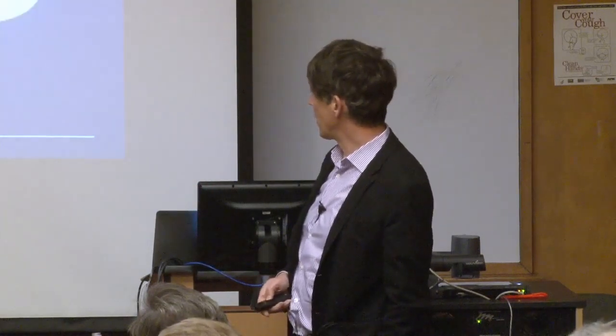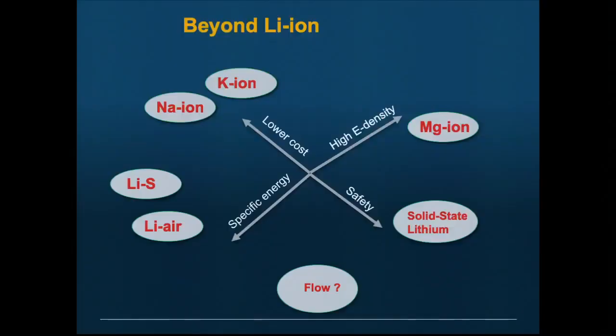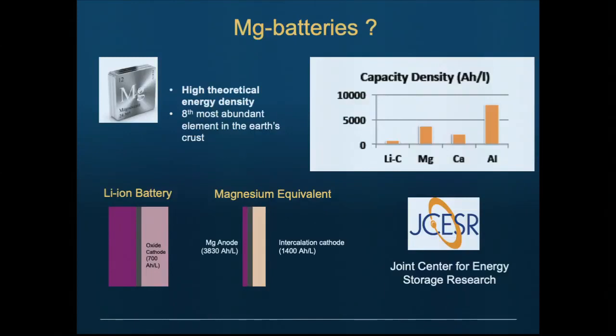Okay, so finally, the last thing, and then I'll close, is: can you go to magnesium ion batteries? Magnesium is really interesting. It's very cheap. It's quite safe, because if you expose magnesium to air or water, it instantly passivates. And that helps you against runaway reactions, right? If magnesium gets exposed to anything, it makes MgO or magnesium hydroxide. And magnesium oxide must be one of the most impenetrable oxides there is, right?